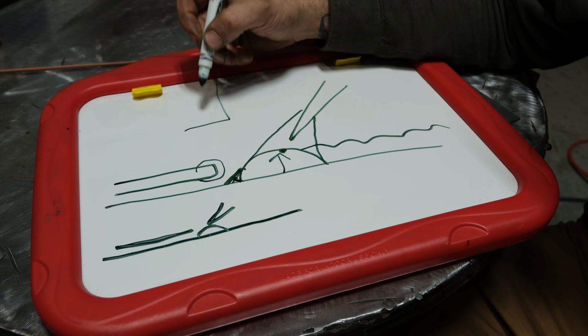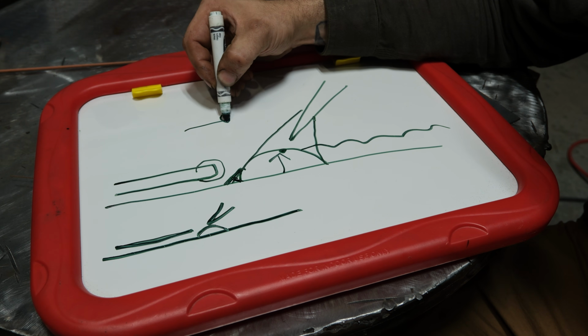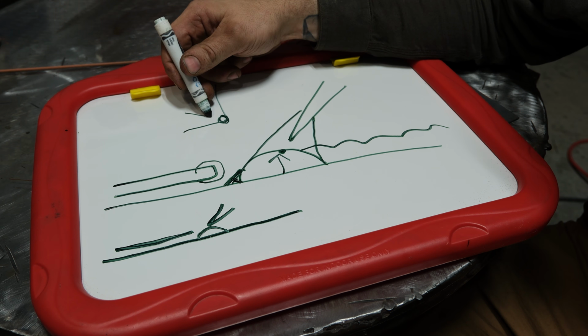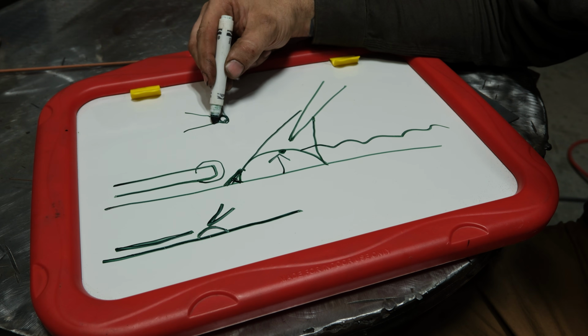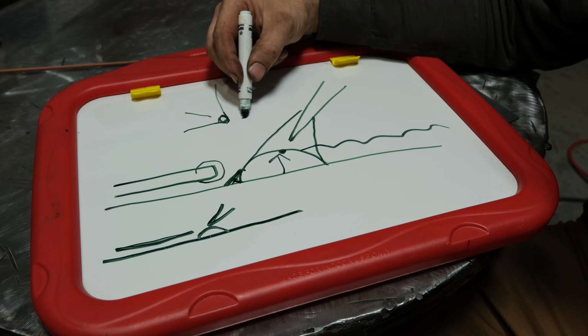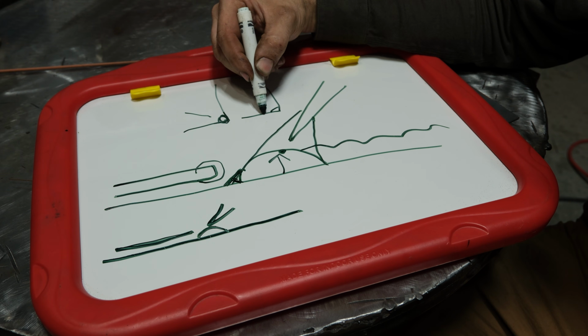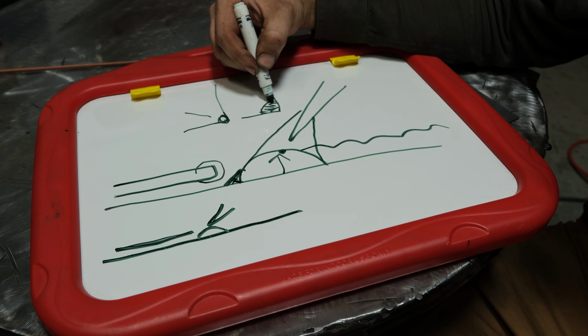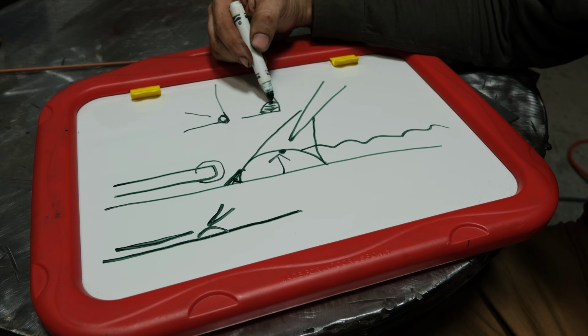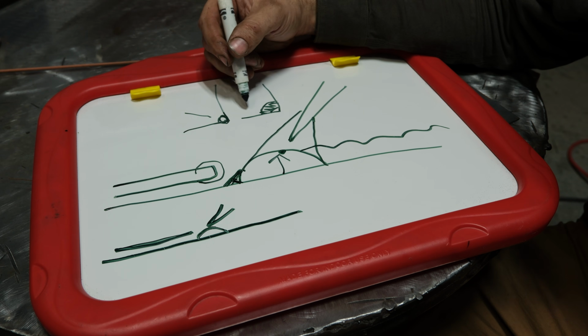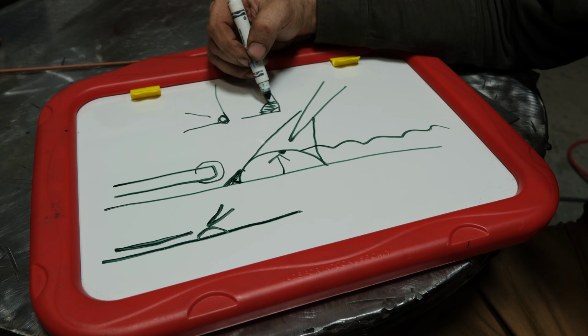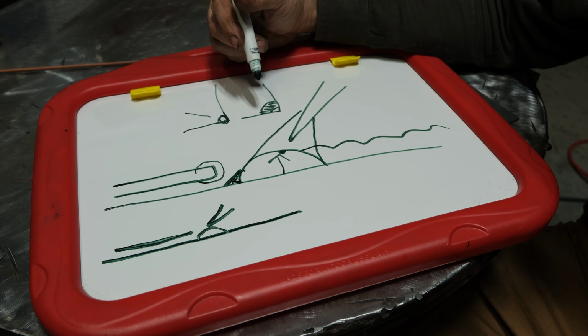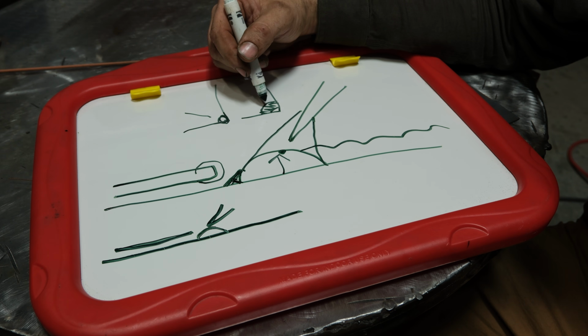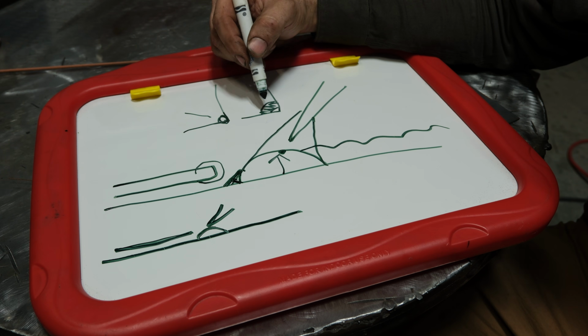So on a fillet weld, if you just lay that sewer pipe, whatever rod in there and then come in with the heat, what can happen is you get zero root fusion. The weld will bridge over the root and it can produce an extremely weak weld. You don't want that. To do lay wire effectively, you must run very high amperage. It's a must. You can't use low amperage and expect good results. It's entirely possible the weld will look decent to you, but the internals will be junk.